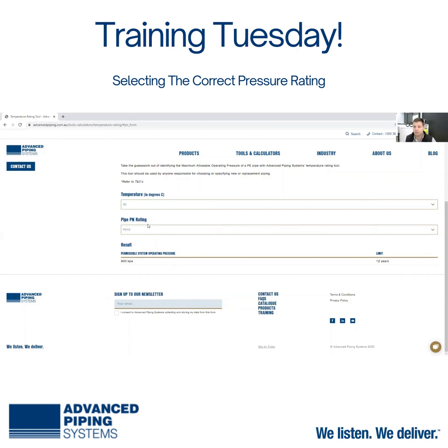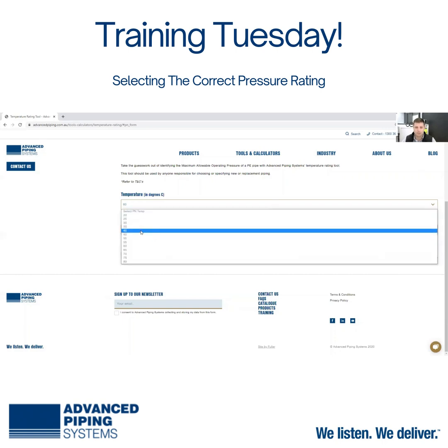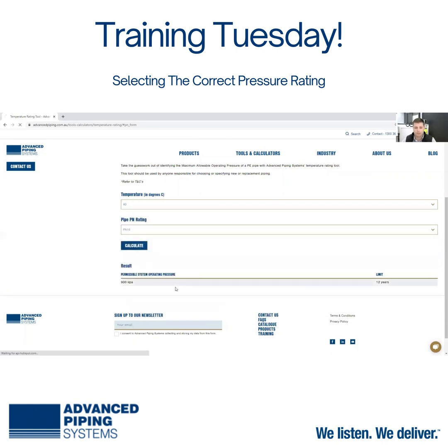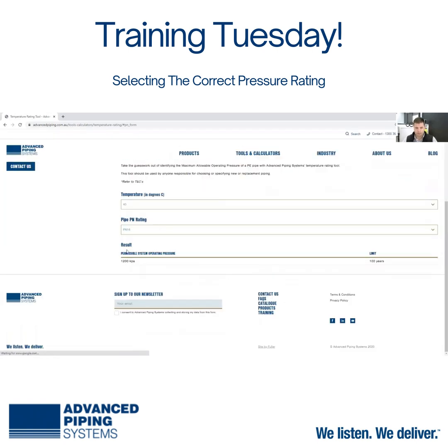So you need to spec up your pipeline if it's going to be that hot, and it's going to be running at 900 kPa. You can also see here that the lifetime limit drops rapidly at that sort of temperature, so 12 years. But obviously that's a very high temperature, it's not common. So if we say drop it back to 40, we can see here that the permissible operating pressure goes back up to 1200 kPa and gives you a limit of 100 years, which is pretty cool.